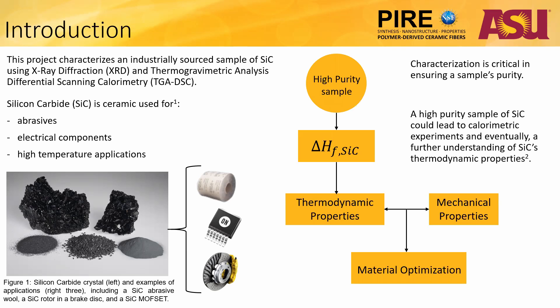Silicon carbide, abbreviated SiC, is a ceramic used for abrasives, electrical components, and certain high temperature applications, such as brake discs, due to its high level of hardness, temperature resistance, and corrosive resistance. Characterization is critical in ensuring a sample's purity, and if we attain a SiC of high purity, then next steps after characterization would involve performing calorimetric experiments in determining SiC's heat of formation by elements.